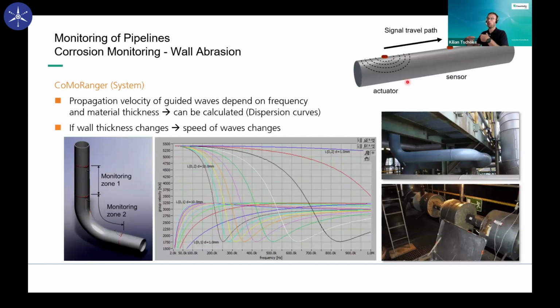As you've seen, if we have more sensors, then we can get more information. But even this easy system, only 2 sensors and 1 measurement box, can monitor your pipelines permanently for corrosion, especially in critical areas. And one big advantage is you can put these sensors on positions where you have access to, and you can monitor areas where you do not have access to, for example, elbows in a really complicated structure, or again, in power plants under insulation.